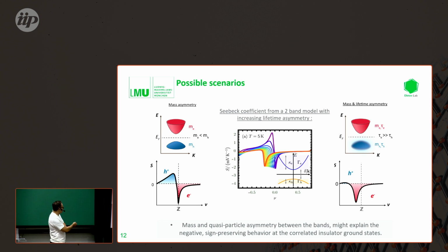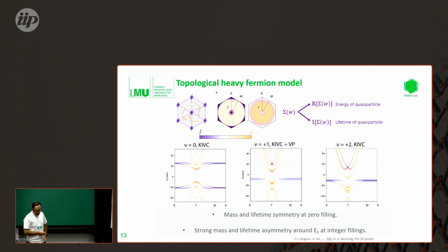So the necessary ingredient to suppress this whole contribution here is that we also introduce some lifetime asymmetry, where we assume that the heavy electrons are very short-lived, meaning that they contribute to the transport coefficient, basically they contribute to the Seebeck effect very weakly, and the signal can be very, very strongly suppressed because of the lifetime asymmetry.